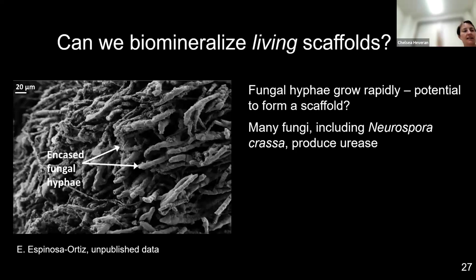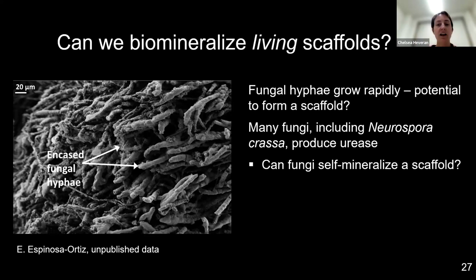Moving forward at Montana State, we've wondered if we can take other strategies here. So one of our strategies is to use an entirely different sort of biological scaffold. And a candidate that we were interested in very early was using fungal mycelium as a scaffold. And this is not random. This is because many species of fungus grow really quickly, and they can have their own biological activity. So species like Neurospora crassa produce urease. Remember that our biomineralizing microbes produce urease, so maybe it could mineralize itself.